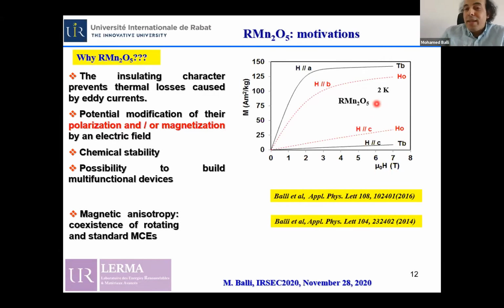Also, the strong anisotropy between their easy magnetization axis and hard magnetization axis will lead to additional thermal effects that can be obtained not by magnetizing and demagnetizing these materials, but by rotating them in a constant magnetic field, which is very, very important from a practical point of view, because with such rotating magnetocaloric effect, you can make a more efficient, compact, and simplified design for magnetic refrigeration.